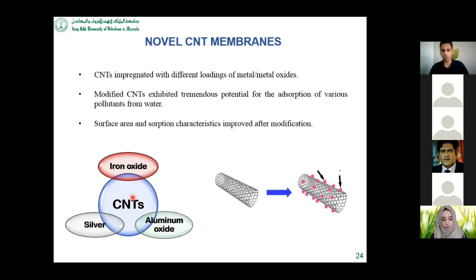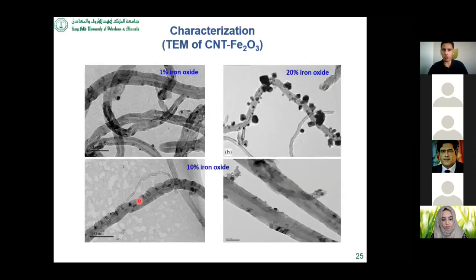And we found that if you modify the surface of the CNT, you will get very attractive features. It improves the surface area, it improves the absorption capacity for various ions and even anions and some organic molecules. But what we did basically, we used this modified carbon nanotube to produce a membrane entirely made of the carbon nanotubes. So this is just TEM images of the carbon nanotube modified with various loading of the iron oxide. You can see here that iron oxide is attached to the surface of the carbon nanotube at low loading. Similarly, at higher loading, some agglomeration of the particle is visible.